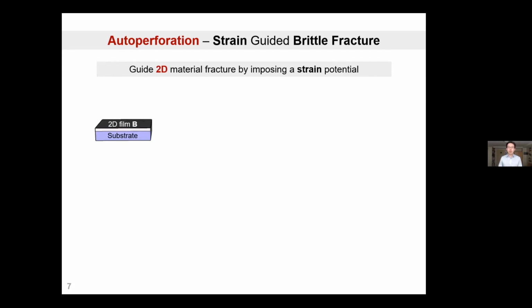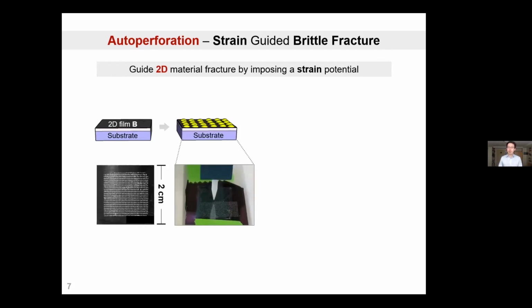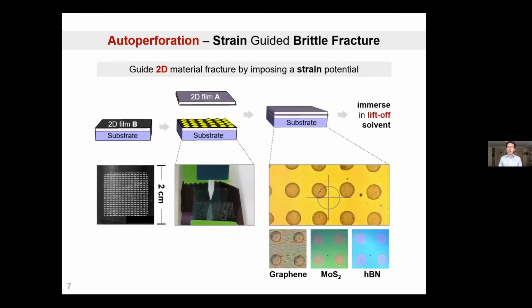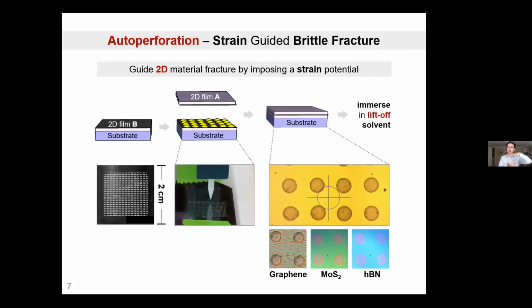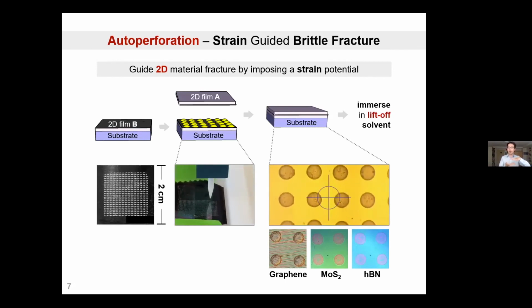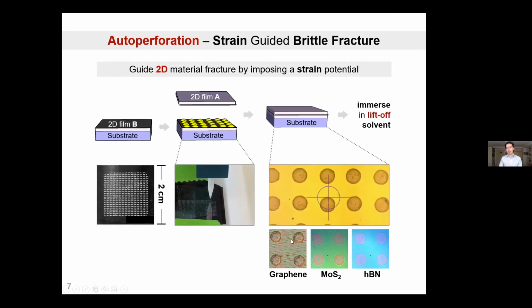The way to do it is actually quite simple. You take one layer of two-dimensional material, and you can print, using an inkjet printer, an array of polymeric dots on top. Each of these dots is about 10 microns to hundreds of microns in size. You dry your dots, take another layer of 2D material, and just overlay it on top. You form this sandwiched array structure. Of course, you can freely choose whatever two-dimensional material you use to form the top layer and the bottom layer. So you can make graphene encapsulated arrays, MoS2 encapsulated arrays, hexagonal boron nitride encapsulated arrays, or you can mix and match, making Janus layers.